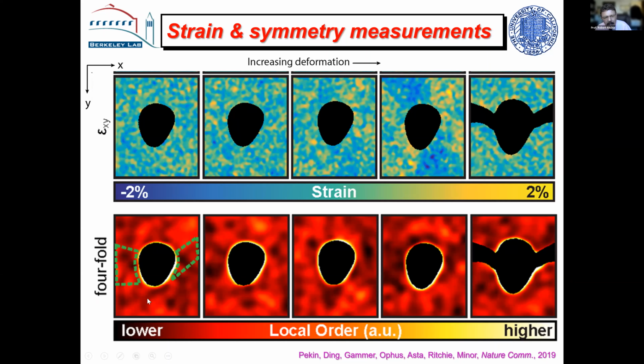And we think we can make out in this region here, the lower degrees of order is where these bands should form. So it's a little bit of a chicken and egg argument, because when you form a shear band, you break the icosahedral order, but there is clearly a link there. So we think this notion of geometrically unstable motifs of atoms and the formation of shear bands may be the key to these very high toughness metallic glasses, because they can generate multiple shear bands and ductility.